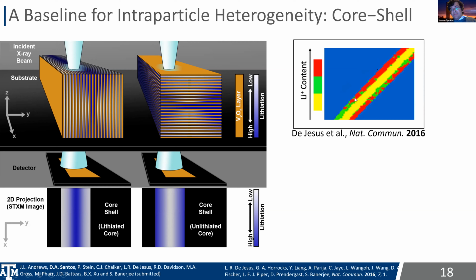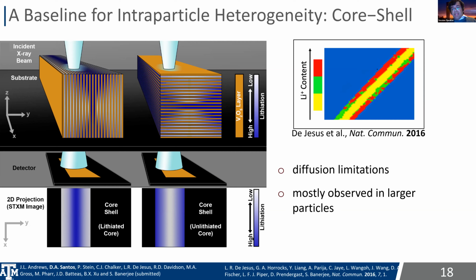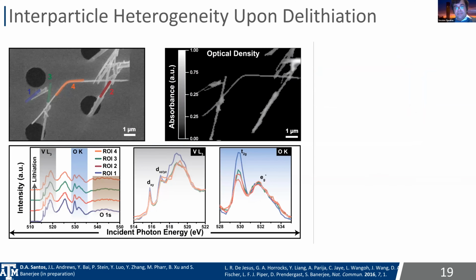This is again some characteristic data that points to the formation of small polarons in V2O5, and really the primary diffusion limitations that arise from small polarons. And I also want to take a second to say that small polarons are quite ubiquitous in most of these oxide systems with large band gaps. This is generally how electron density accumulation will result in small polarons being stabilized.